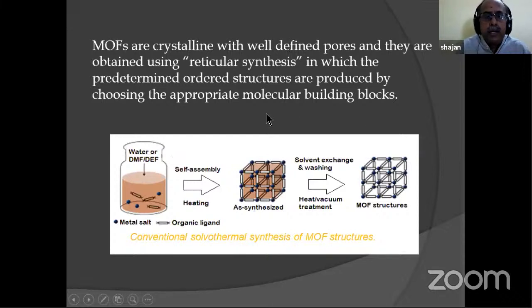For MOF, a simple solvothermal process is normally used. You have to take a solution containing some solvent, maybe water or DMF, which is an organic solvent. You put inside the salt as well as the organic ligand, and they will combine and you will get a structure. Now, as I said earlier, you have to do a solvent exchange and heat in a vacuum, and now all the solvents are removed, and you will get a network structure like this. And this is called a metal organic framework. Both are preparatory methods. Here we are using a simple solvothermal method, there we are using a sol-gel.